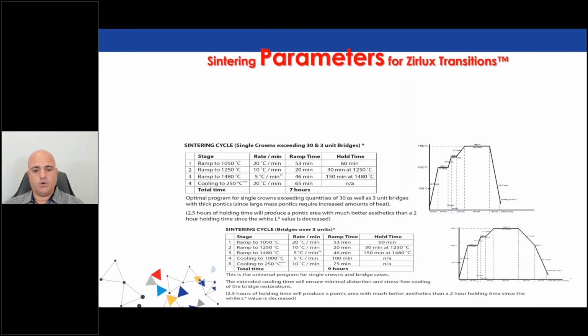If you're too quick with your sintering temperatures, or especially your decrease numbers, meaning your cooling, and it's a very large mass, so certainly a large bridge, it may create a heat shock and create dire consequences, which is not something that we want. So there is the 9-hour cycle, but you can do a tremendous amount of restorations or solutions within that. It doesn't matter if it's a long span bridge or multiple individual units, whatever you can fit in there, it's perfectly fine in the 9-hour sintering cycle.